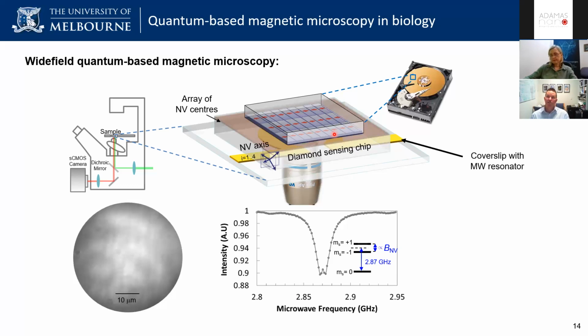But the challenge is, once you bring them really close to the surface, how do you keep them in the negatively charged state for long enough and maintain their coherence properties? How do you functionalize the surface to reduce all of the magnetic noise and electric noise? So it depends on the application, and it's a trade-off between coming closer, but then being noisier in terms of the surface and things like that.